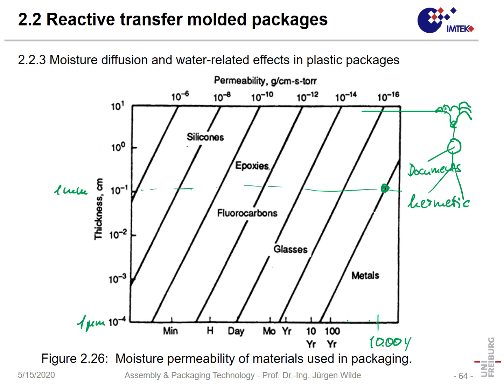On the other hand, if we have ceramics, they can also be quite tight against diffusion. Ceramics sometimes have some defects, so there could be a little permeation, but ceramics are similar to metals, and they prevent mostly permeation of moisture, and they are almost as, let's say, powerful in making hermetic seals as metals are. Glasses are less good. Moisture diffusion is much faster in glasses than in metals or ceramics, but still glasses can be used for hermetic sealing. Then polymers are worse.